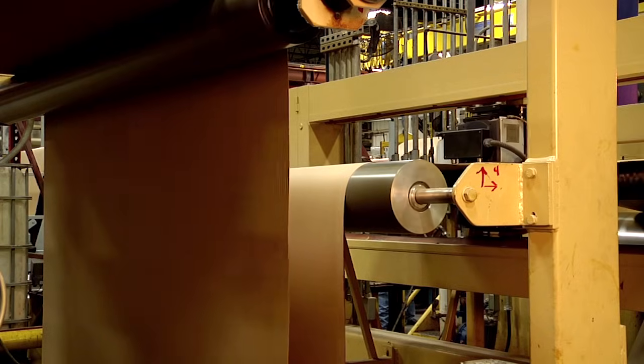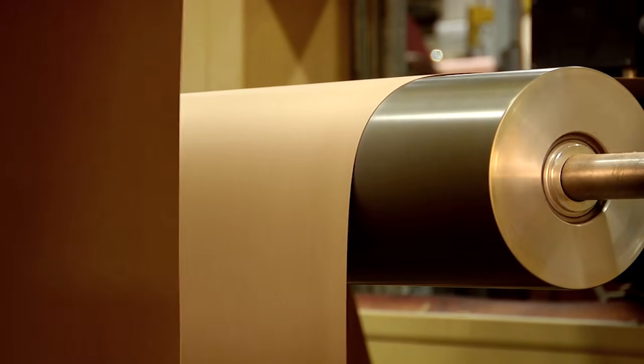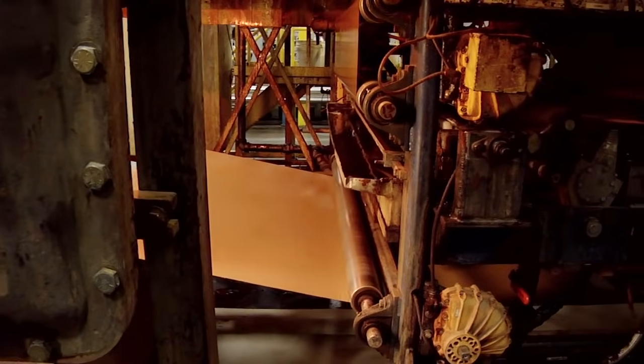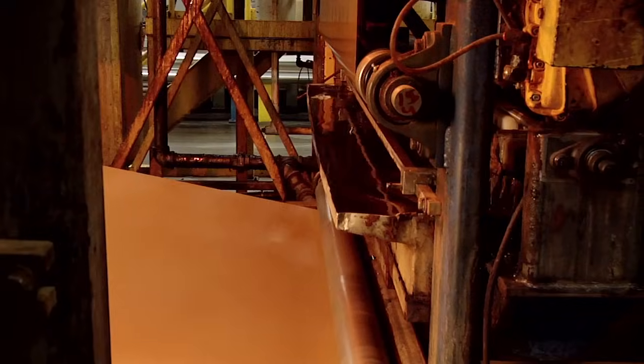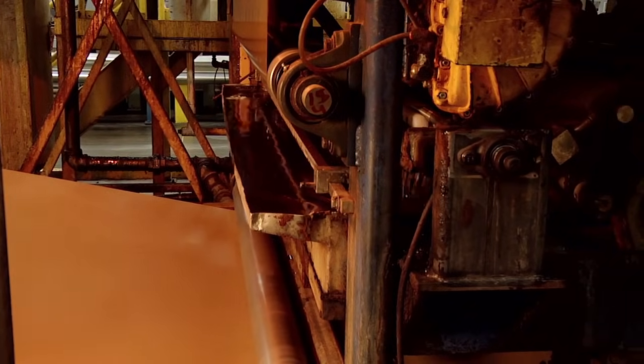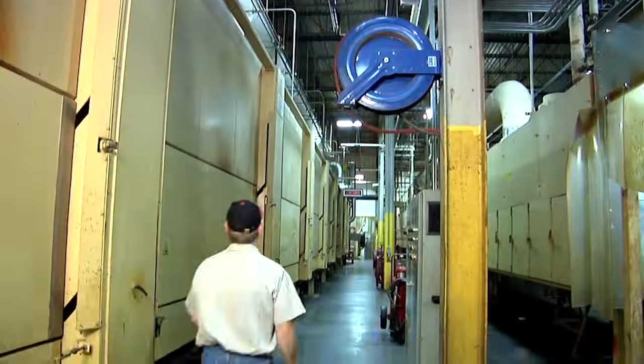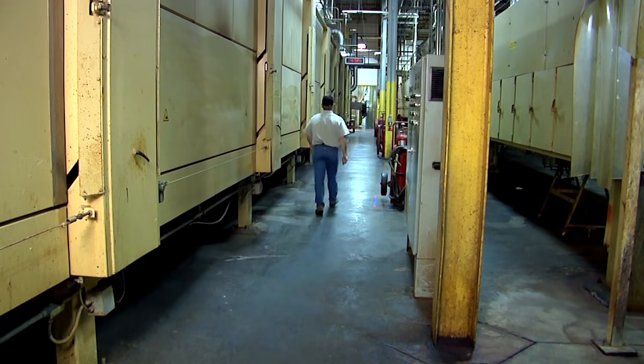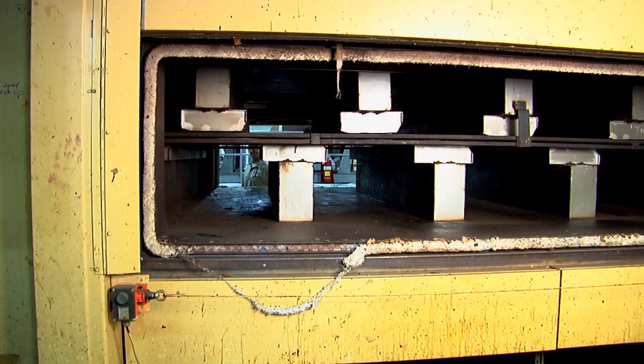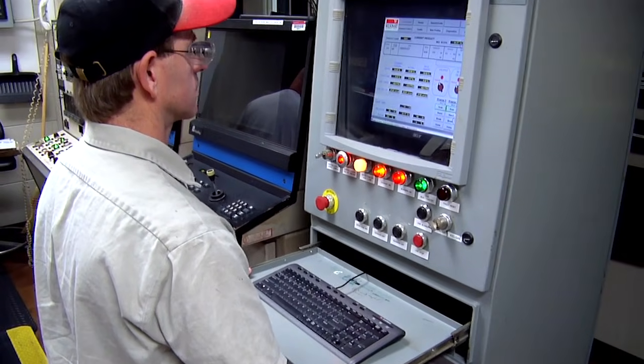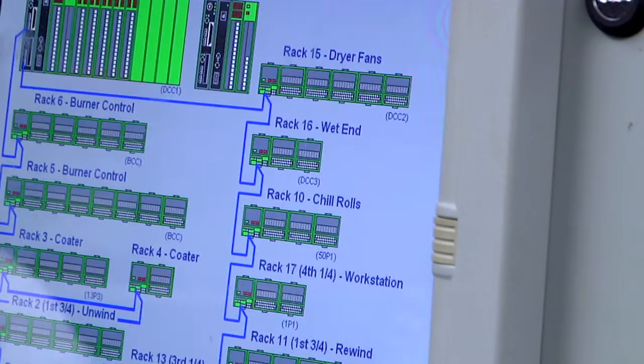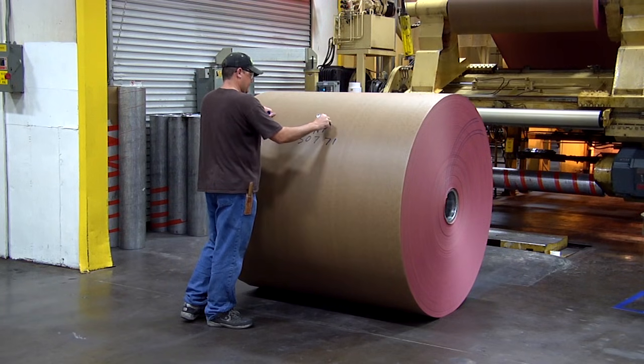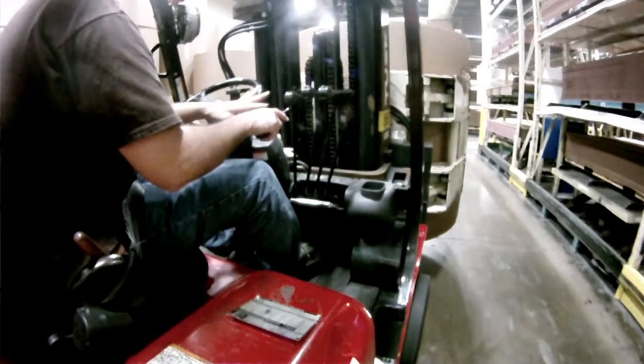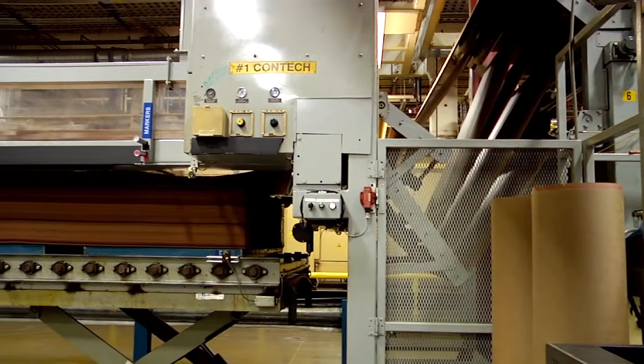As the paper is unwound, on the way it goes through a variety of tension rollers before it actually hits the phenolic coating system, a patented process which is actually a bath filled with phenolic resin. At that point, the paper comes in contact, is saturated, then fed into the oven, where it's then dried. That paper actually floats through each one of those zones in the oven at a particular type of temperature. Once it exits the oven and is cooled, then that paper is rewound back on a large spool and then transferred over to an area where it's cut and then ready for assembly.